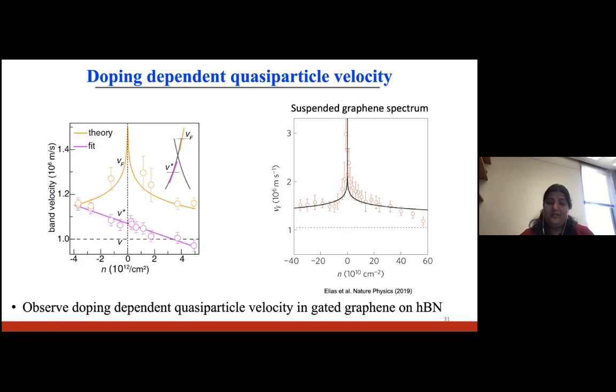The take-home message is that our results here confirm that the quasi-particle velocity in gated graphene on hBN is doping dependent, and it is due to these Coulomb interactions.